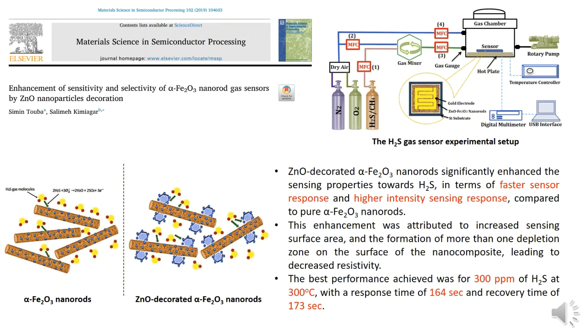Let me start with this first example. This paper is titled Enhancement of the Sensitivity and Selectivity of Alpha Ferrous Oxide Nanorod Gas Sensors by Zinc Oxide Nanoparticles Decoration. Here, alpha ferrous oxide nanorods were decorated using zinc oxide nanoparticles, which significantly enhanced the sensing properties towards hydrogen sulfide in terms of faster sensor response and higher intensity sensing response compared to pure alpha ferrous oxide nanorods.